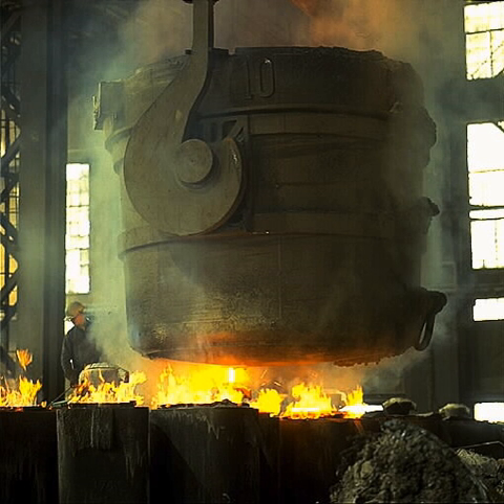Topic: White cast iron. White cast iron displays white fractured surfaces due to the presence of an iron carbide precipitate called cementite. With a lower silicon content, graphitizing agent, and faster cooling rate, the carbon in white cast iron precipitates out of the melt as the metastable phase cementite, Fe3C, rather than graphite.